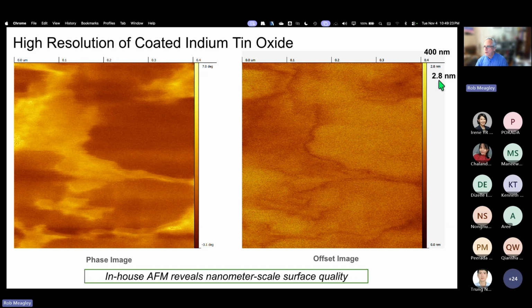The step height here that we're detecting between the yellow and the dark red is about 2.8 nanometers. And so, as Chen-Shu noted, you can get sub-nanometer resolution if you try. And in this case, I think you'll see that the color gradient supports that quite well. In this 400 nanometer by 400 nanometer field, we're able to pull out truly remarkable detail in terms of the surface quality and the nature of this complex material. By and large, I don't think there is a better, more versatile AFM instrument out there.